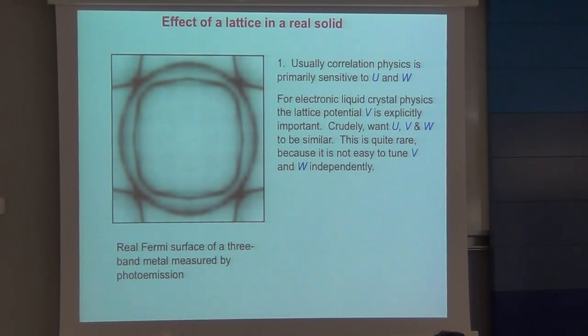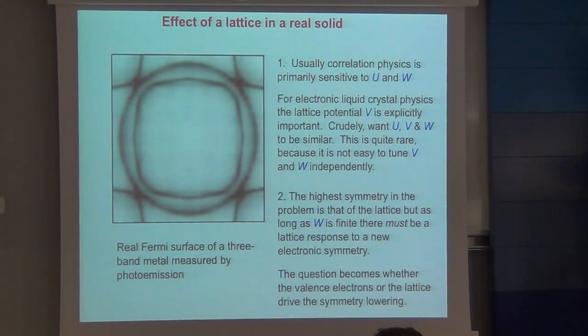So in general, as you try and make a solid more interesting by making the correlation strength closer to the bandwidth, you're also cranking up the lattice potential, so whatever state you get has a higher probability of respecting the symmetries of the lattice. So what you need to do for the electronic liquid crystal game is to find a way of breaking this. You want to be able to tune the bandwidth independently of tuning the lattice potential. And I'll try and cast the experiments I tell you about in those terms.